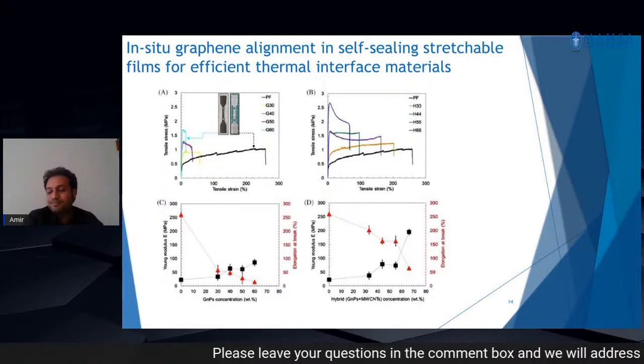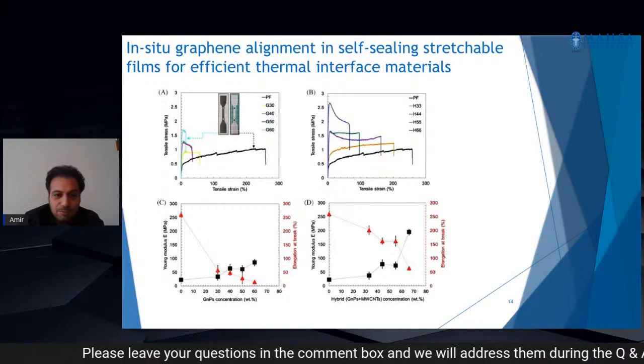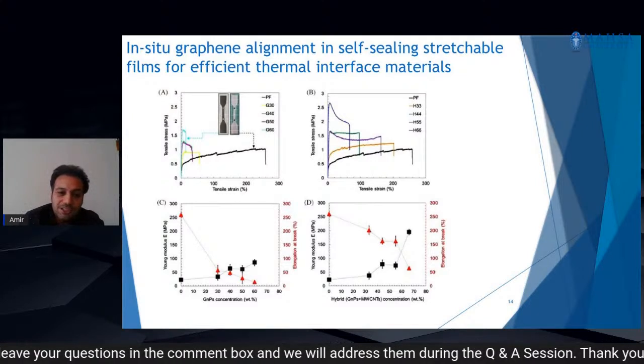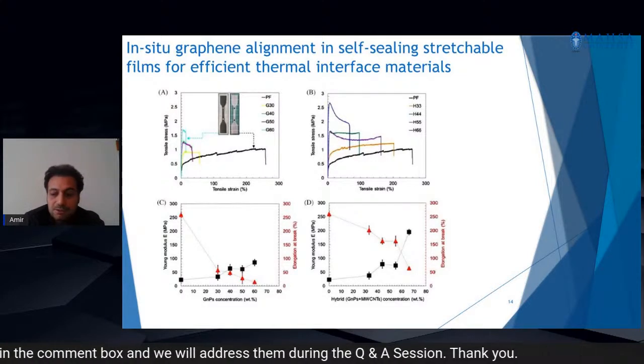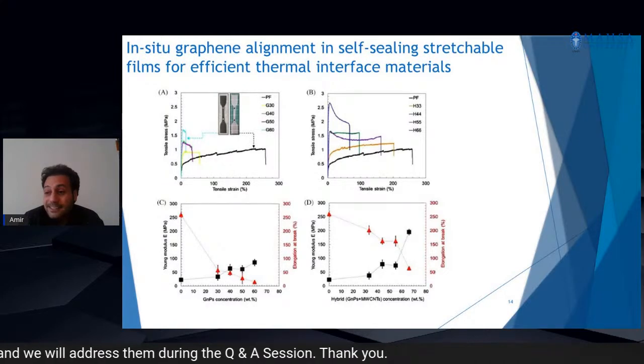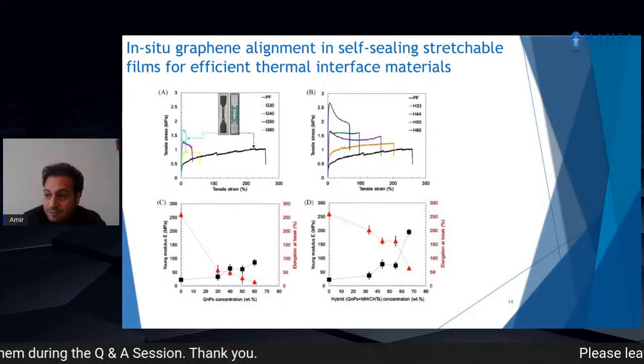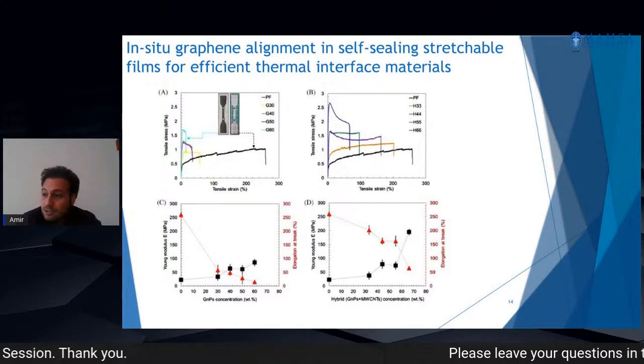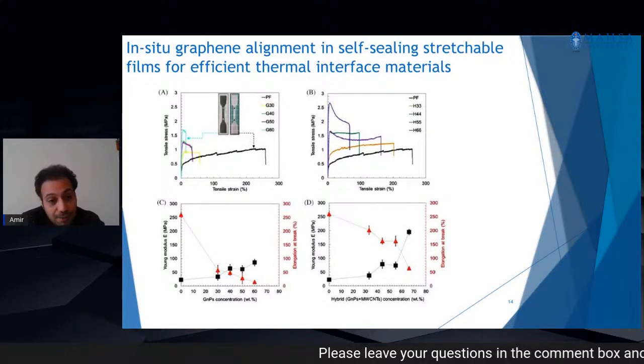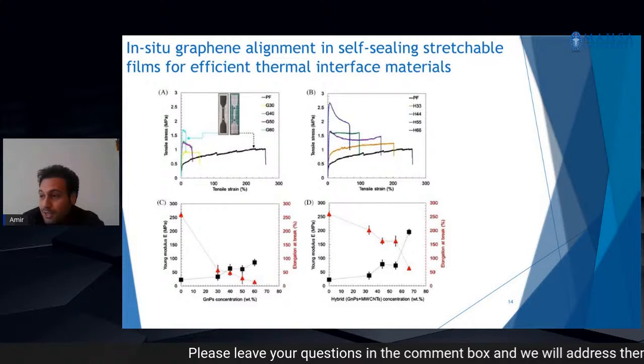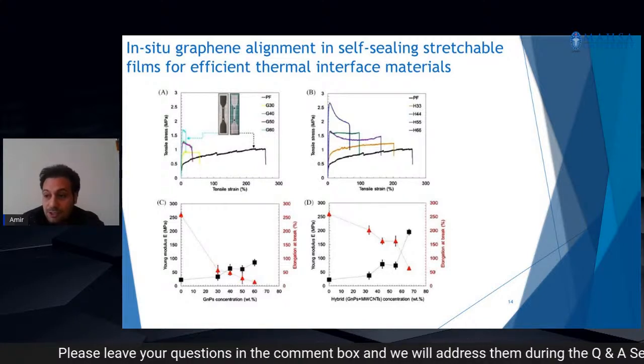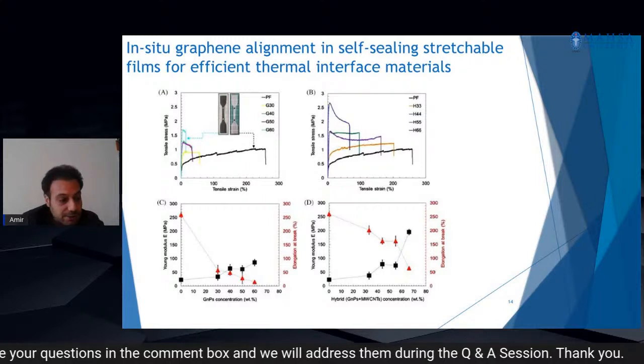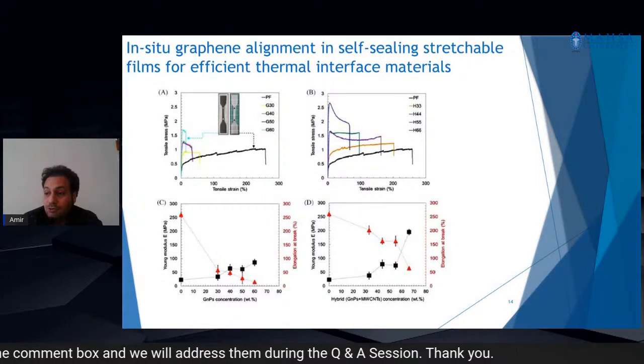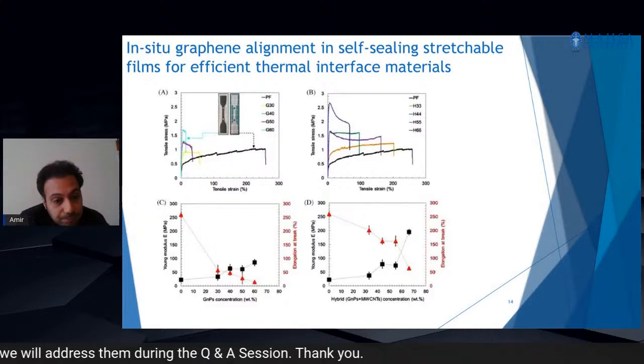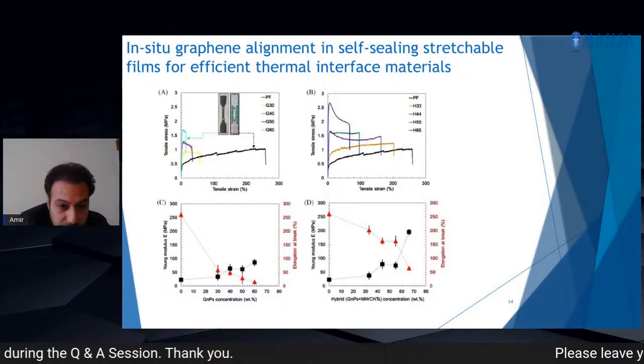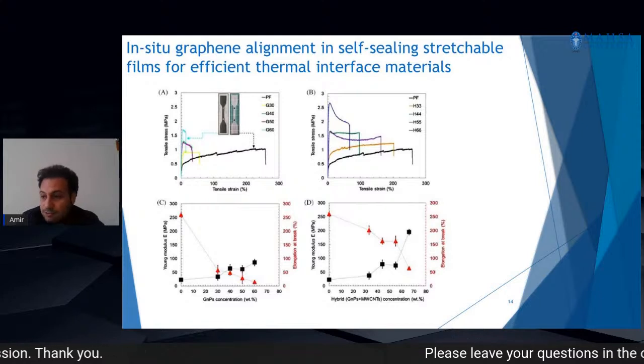Here, for mechanical properties, we are trying to check the mechanical properties of the sample. Here are the stress-strain curves of different nanocomposite samples containing only GnPs in A, and with hybrid content of the GnPs and the MWCNTs, as well as the unfilled PF matrix. It's clear on the left side of the plots.